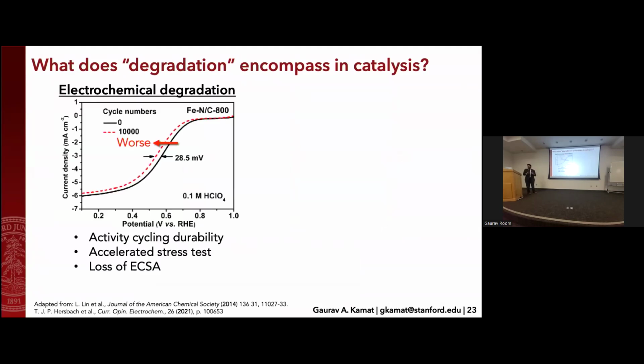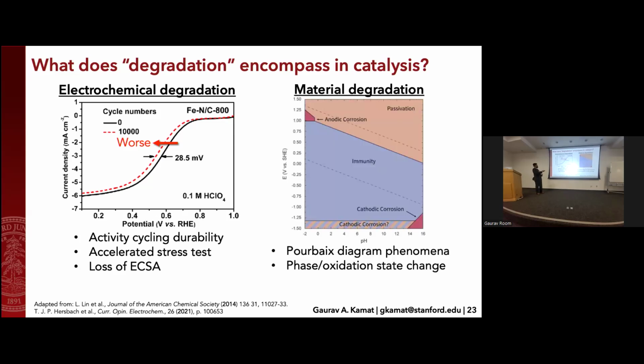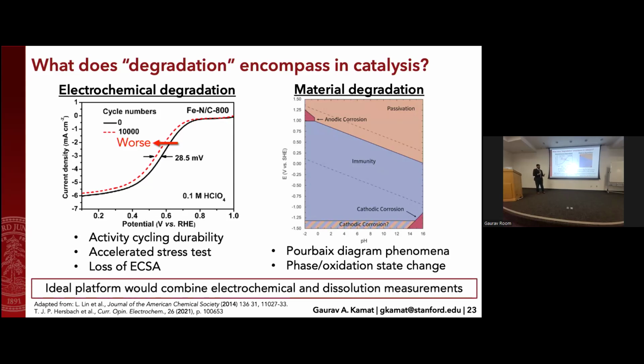And what degradation means in catalysis is not necessarily a well-defined term. You have things like electrochemical degradation, which means as you cycle this thousands and thousands of times, you start to move your cyclic voltammogram left and have a lower activity. And that's purely an electrochemical measurement. But as we mentioned before, you can also have material degradation, where you can have ions coming off of your surface, phase changes, oxidation state changes. An ideal system would be able to combine elements of both of these so that we could actually understand what's going on.